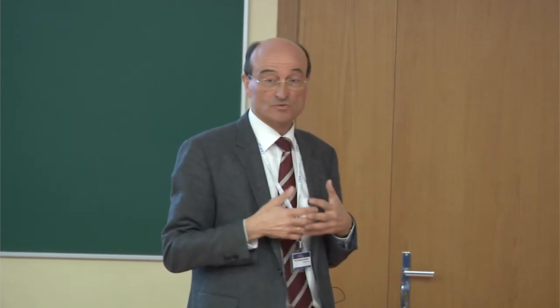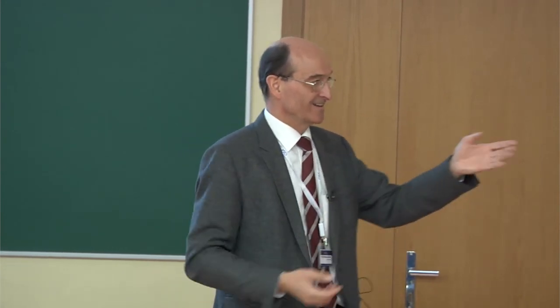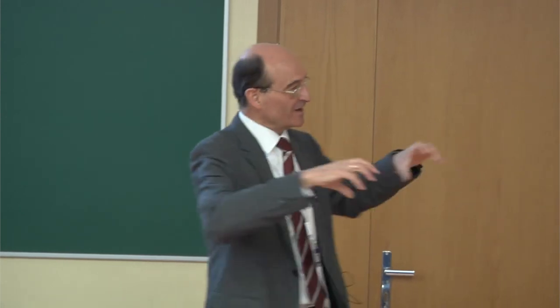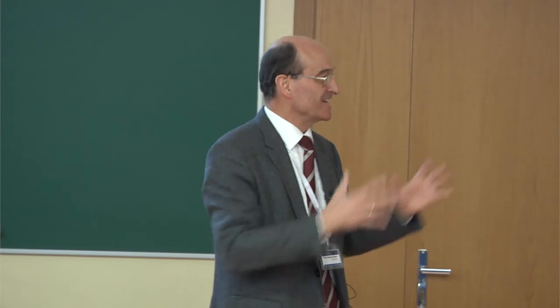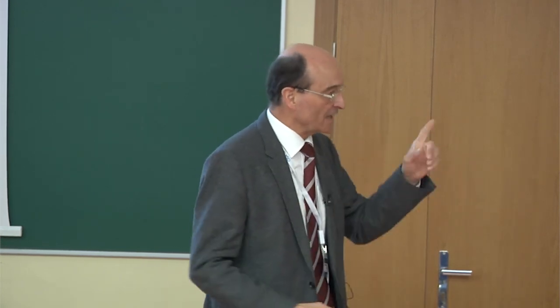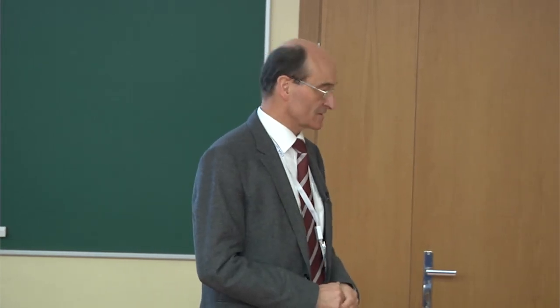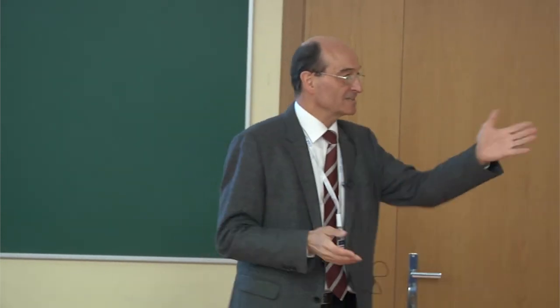So obviously, there has to be a thermodynamic relaxation gain for the material. So if the material can relax, the surface energy is high, the surface tension is high of the original material, then there is a good reason to relax and to reorganize. And materials which have a low surface energy, and polymers, they are large molecules, spaghetti-type interactions, yeah. They start out probably with a rather low level of surface energy, and they do not have the reason to reorganize. You can, however, do interference patterns on polymers. It works. But then they are sub-micrometer. Yeah? So we are still trying to understand that, but I think the surface energy is very, very important. There has to be a reason for the material to relax thermodynamically. The kinetics we trigger with non-thermal melting.